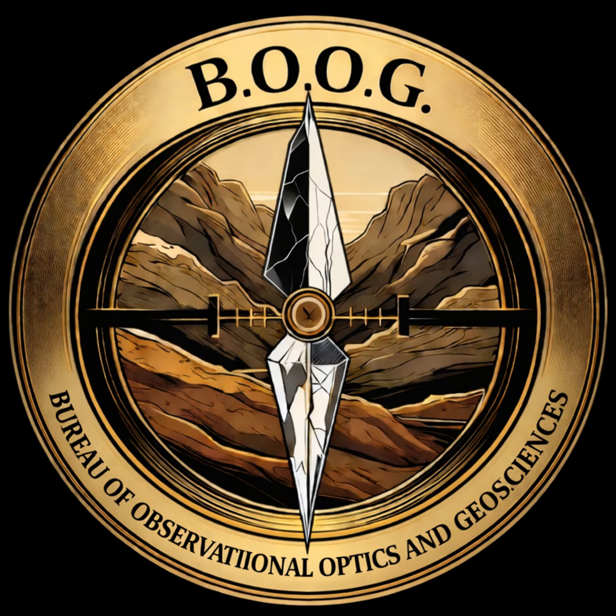It genuinely glows. Exactly. We established that the chromium ion is responsible for the red color. But chromium serves a dual purpose within the corundum lattice. Okay, what does it do? When chromium is exposed to ultraviolet light, it absorbs that high-energy UV radiation and re-emits it as lower-energy visible red light. It fluoresces. And you don't need a special black light for this. No, you don't need to be in a nightclub with a black light to witness this. The natural ultraviolet rays present in everyday sunlight are more than sufficient to trigger this reaction.